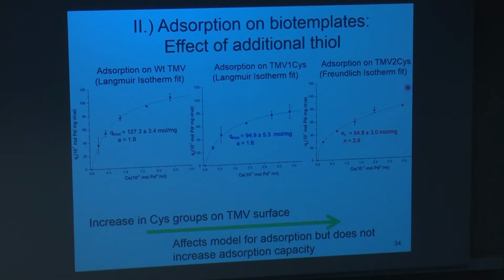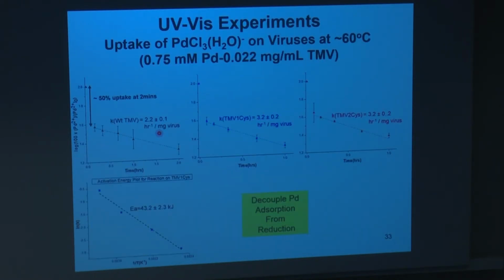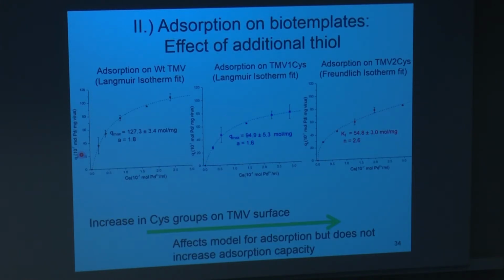So, yes, when we look at the adsorption capacity of palladium on the TMV, that's not reactive, just a palladium ion adsorbed on the TMV, we can look at that, and it does indicate that the first data point should probably be somewhere about 1.8 to about 1.7. That first data point, if you look at the amount of palladium that's adsorbed on the TMV. So that was encouraging, but it also shows that there is some reaction that's probably occurring that's causing that drop as well. It's not just due to adsorption.